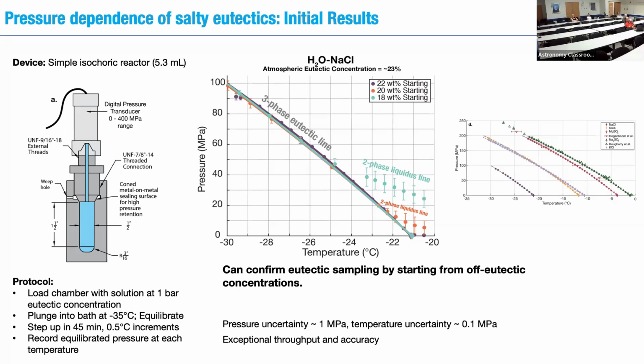We did some sort of thermodynamic due diligence where we tested a variety of off concentration eutectic starting compositions, I should say non-eutectic starting compositions. And you can see here that we get the behavior that we should expect from Gibbs phase rule, where for two-phase equilibrium, so just the liquid and ice, there should be a variety of different starting points in concentration that will yield a variety of different curves.